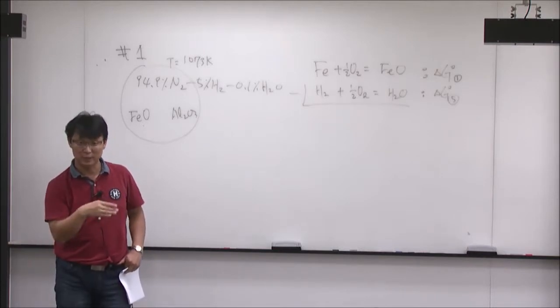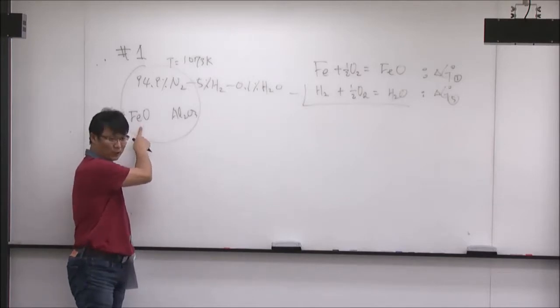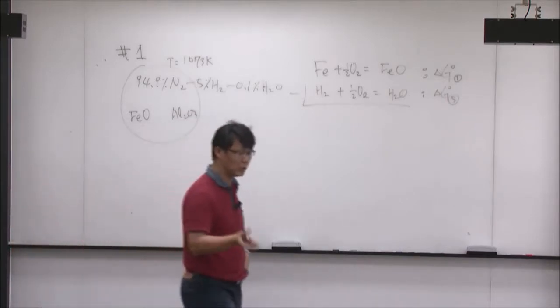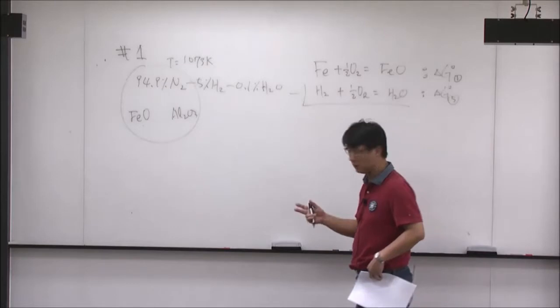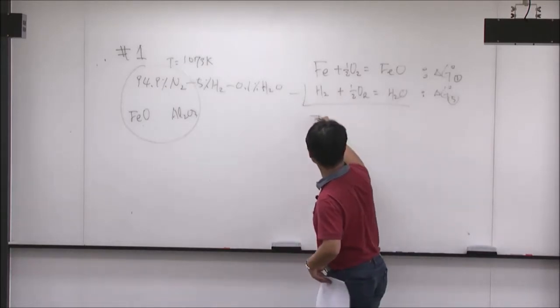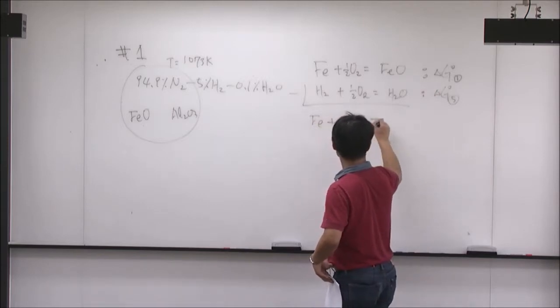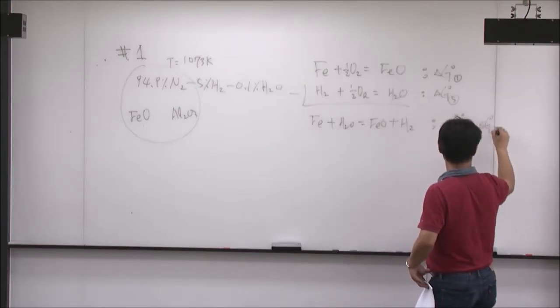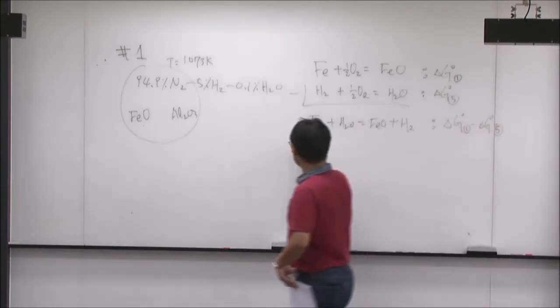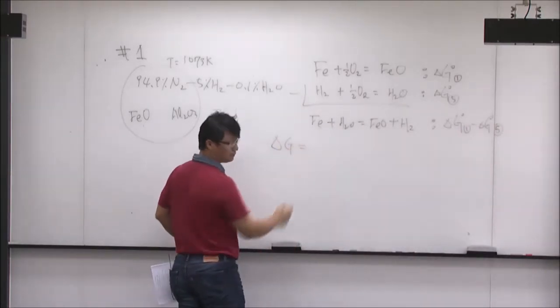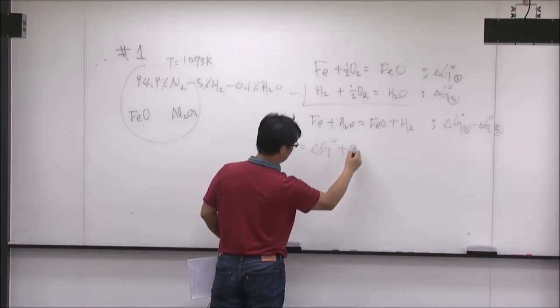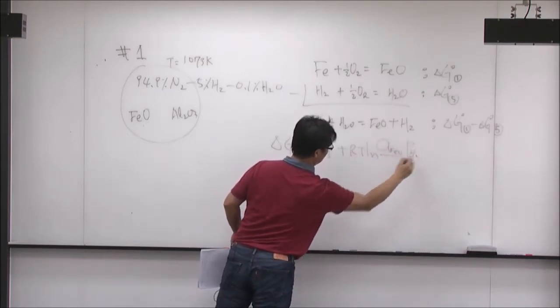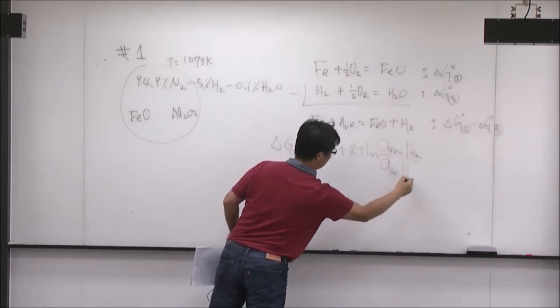This is not an equilibrium state — I'm asking the direction of the reaction. So when you look at the direction, you have to check whether delta G of reaction is positive, negative, or zero. If you do this, delta G of reaction equals delta G0 plus RT·ln(a_FeO · P_H2 / a_Fe · P_H2O). I assume all the solids are separate phases with activity equal to one. So P_H2 is 0.05 ATM and P_H2O is 0.001 ATM.